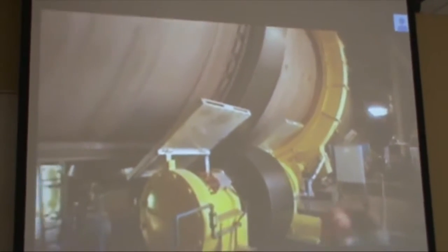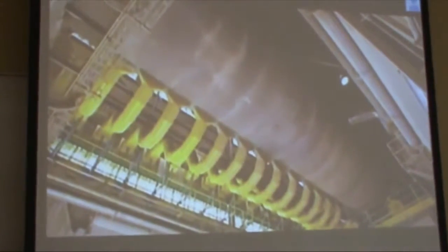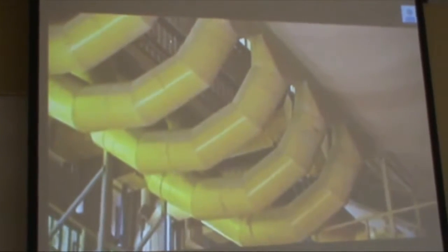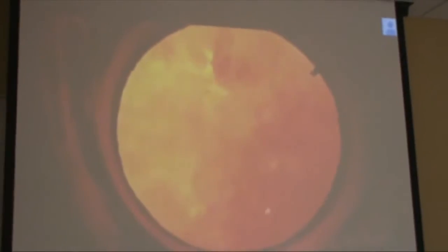The powder enters a preheater at 80 degrees Celsius and within 40 seconds gets more than 10 times hotter, beginning the process of bonding minerals. A flash calciner removes 95% of the carbon dioxide in about 5 seconds, isolating the lime — the most important element in cement. The powder then moves into a rotary kiln, a huge cylindrical furnace set at an angle so material travels 49 meters from top to bottom. The kiln rotates about two turns per minute. The burner's gas flame reaches 1,600–1,700 degrees Celsius, and as the powder reaches 1,500 degrees it fuses into marble-sized pieces called clinker.